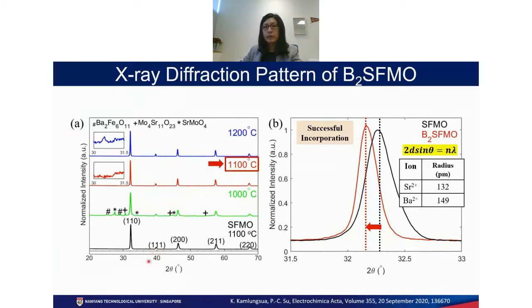So we look at the peak around 32 degrees, and we can see that there is a clear shift of this peak, slightly away from its original position, meaning that our barium, because of its slightly bigger radius, is successfully incorporated into the A site.